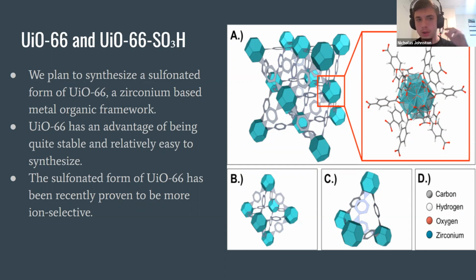And then when crystallization happens and they analyze the surface area, they found it to be a very high number, like 1,000-something meters squared per gram, which is pretty insane if you think about it. But then again, the materials are exceedingly small. Another thing with metal organic frameworks is that you can use a modulator to essentially slow down the crystallization process I previously mentioned, to control the growth of it.